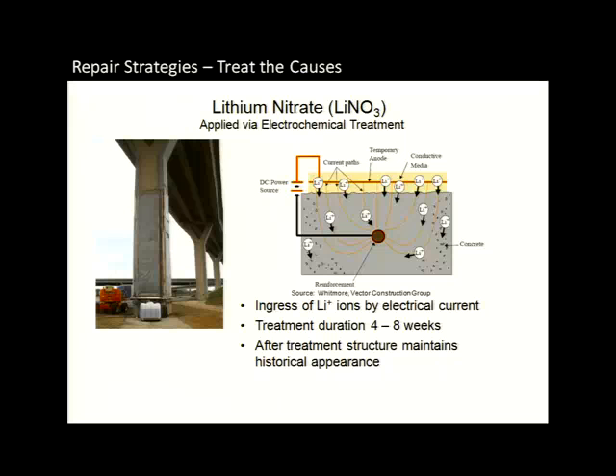So getting back to how we actually tried to mitigate ASR going on in this structure, we used a technique called electrochemical injection. This is a technique that's typically used to remove chlorides from concrete bridge decks. What you basically do is you set up a temporary anode on the outer surface of the concrete. That's what you see here behind that plastic sheeting. You tie into the rebar by drilling into the concrete.